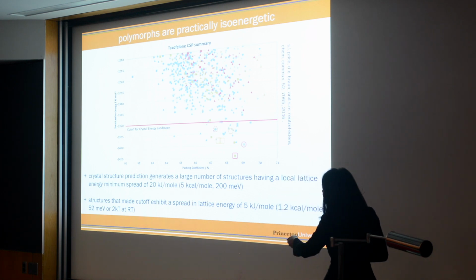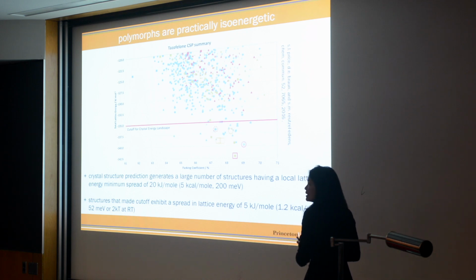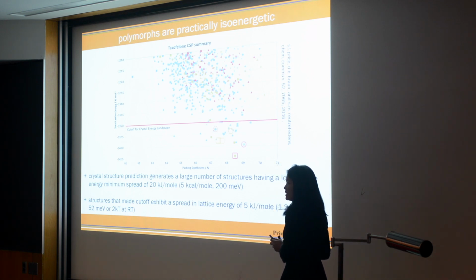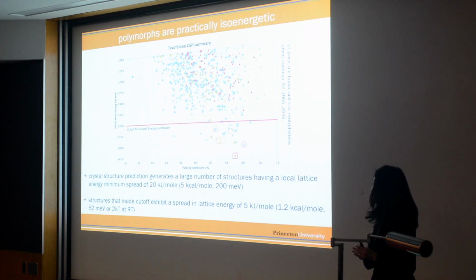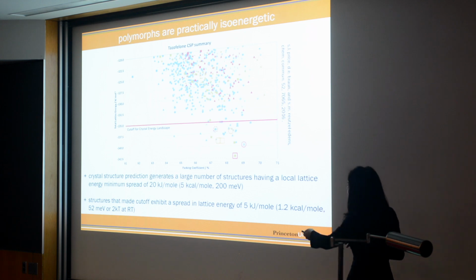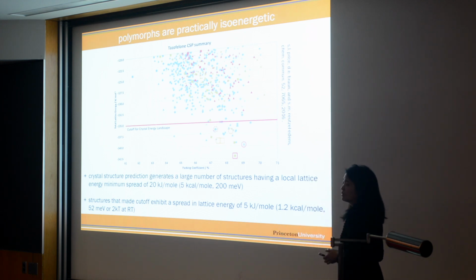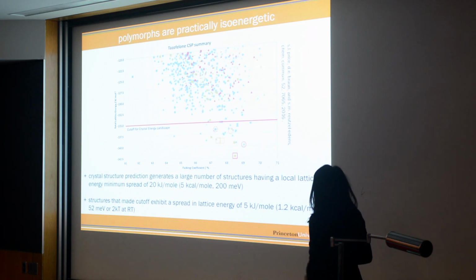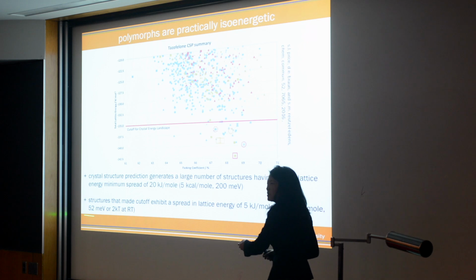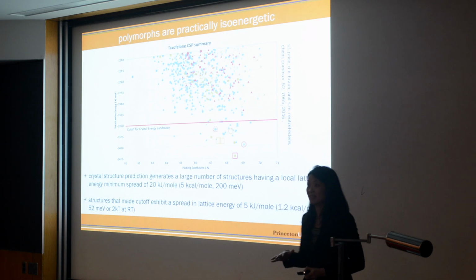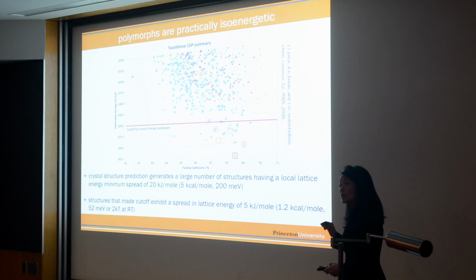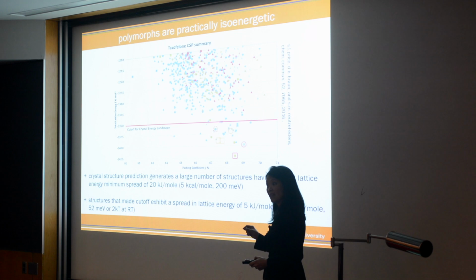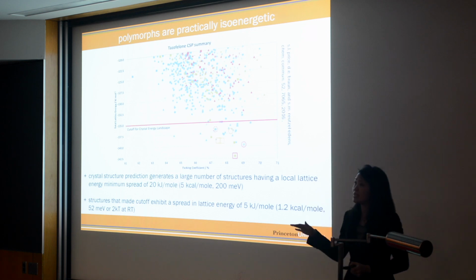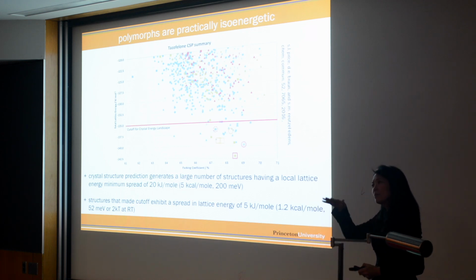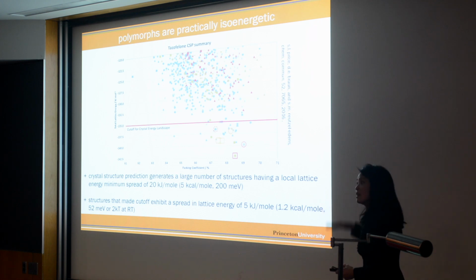What I'd like you to pay attention to is the y-axis here. You can see that the y-axis spans about 20 kilojoules per mole. Not very big. And if you wanted to focus on the lowest energy packing polymorphs because they're more stable, you can focus on the 30 lowest energy polymorphs. And there, the energy spread is even smaller. It's about 5 kilojoules per mole. So that's about 2 kTs, right? Again, this is to say that thermodynamically, the differences between these polymorphs are small. What dictates whether they're accessed or not is really the kinetic constraints. It's how you process and whether you can get over these kinetic barriers. So in terms of the energy landscape of polymorphs, I'd like to think of them as little puddles or little pits, right? I mean, they're shallow little pits on an energy landscape.